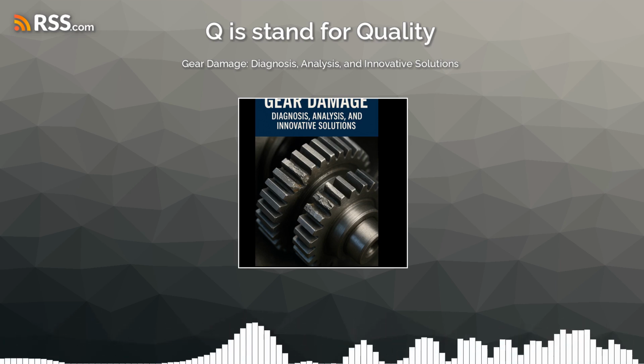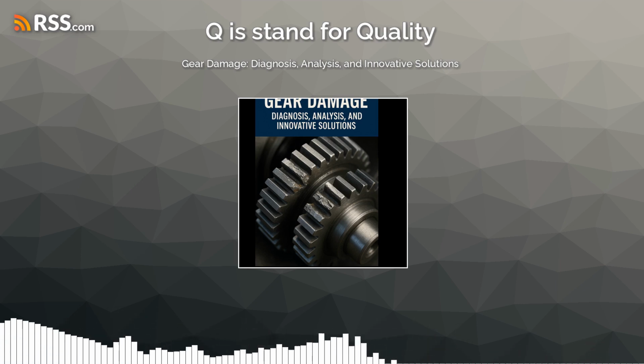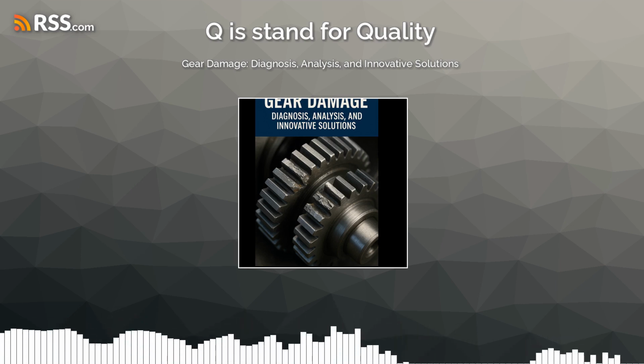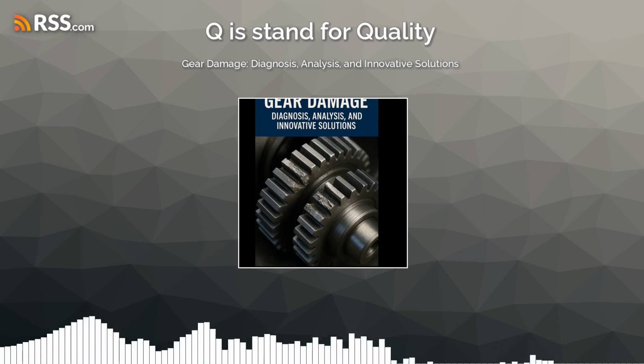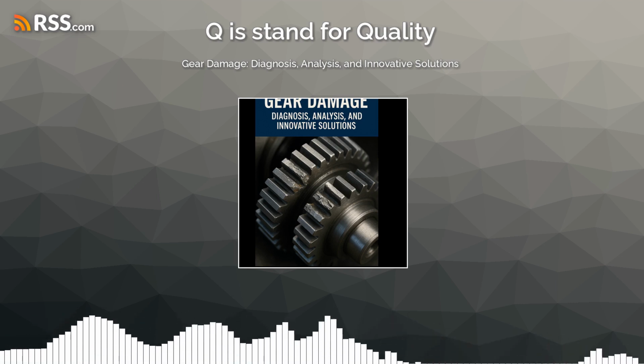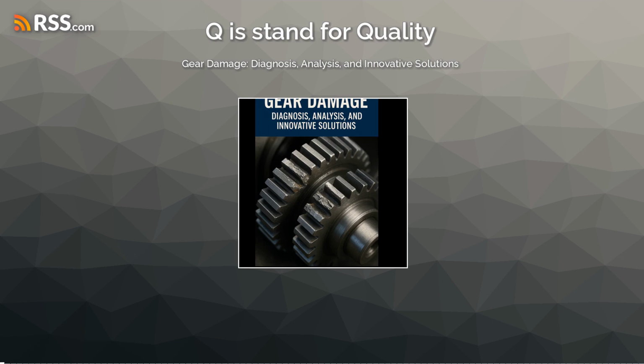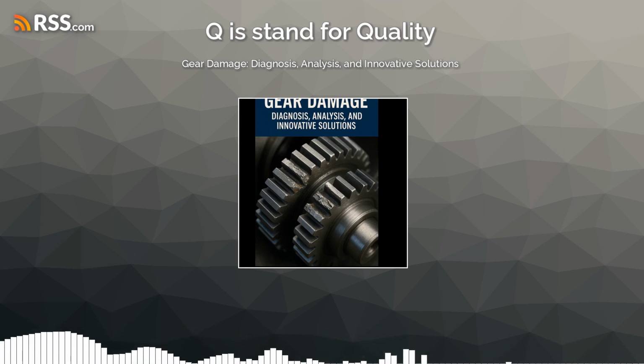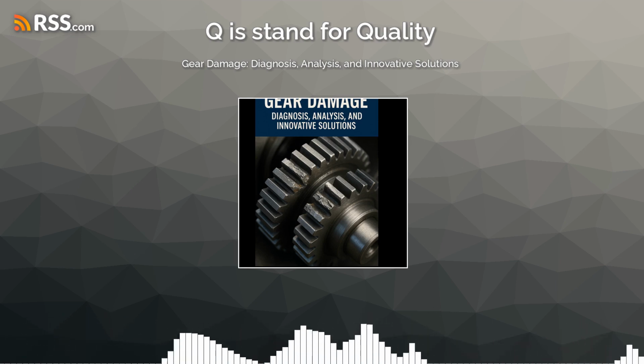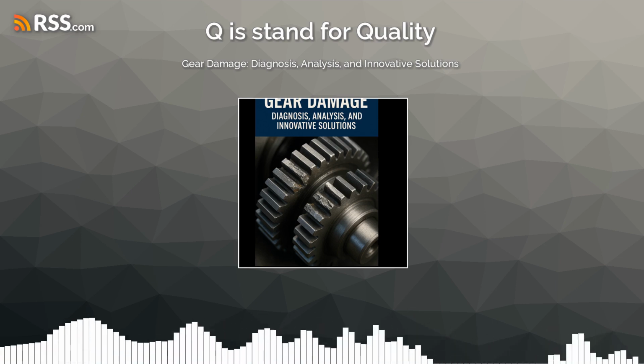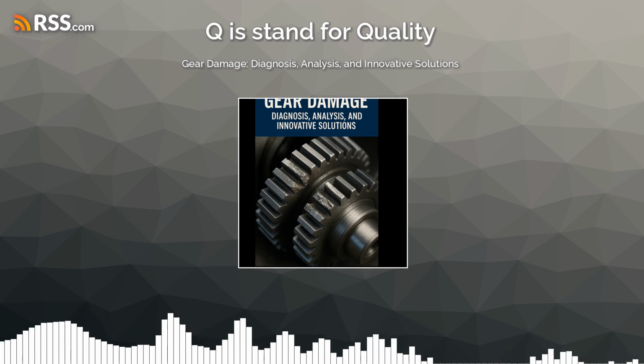And among those, fracture sounds like the really bad one. Unquestionably. The source singles out gear fracture as the most severe failure mode. When a gear fractures, it often causes immediate extensive damage to the whole system. Catastrophic breakdown, not a slow decline. And with fracture, it's important to differentiate between static and fatigue fracture, right? One sounds sudden, the other more gradual. Exactly. That distinction is vital for diagnosis.